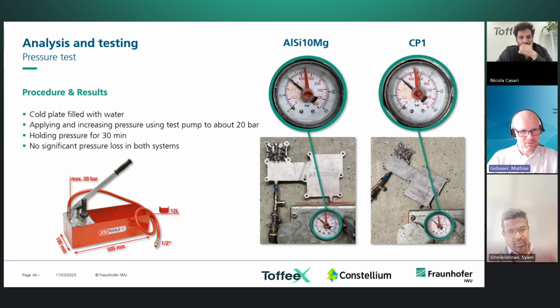Most of the parts, or for this part, have a 1.5 millimeter wall thickness. It's quite thick. But it was interesting to see, is there a difference between the materials? Does it hold? Is it pressure tight, or does it even burst or something like that? So what we did is a rather simple test. We basically filled in water and pumped the parts up to 20 bar, holding the pressure for 30 minutes. We had no leaks, no cracks, nothing. Both of the components survived the torment, and we didn't have any significant pressure loss over time. So we can say both components came out okay.